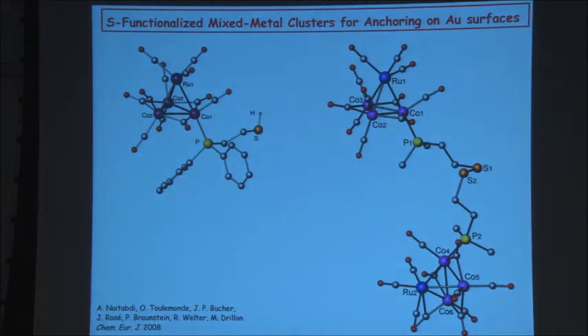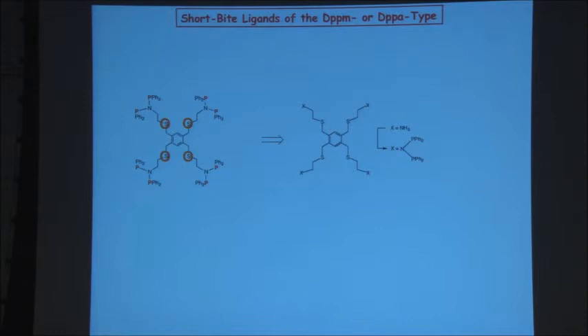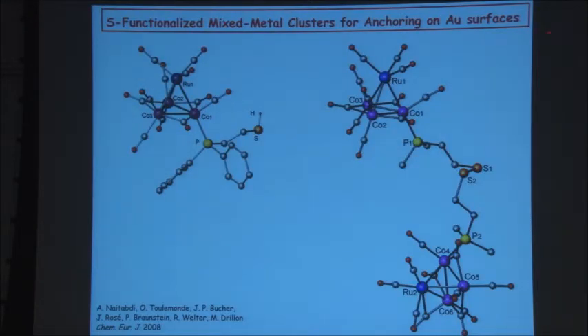And I'm just skipping this one because, no, I cannot skip that one quickly. In the process of looking at these thiol functions, we realized that the thiols here are very easy to oxidize to give you a sulfur-sulfur linkage, a disulfide. So you can link two such clusters with the S-S link. But the beauty is, if you take this cluster, which is much more stable towards air than the thiol, on the gold surface, the gold surface will break the S-S bond and form directly a S-gold interaction. So basically you attach two clusters in one shot.